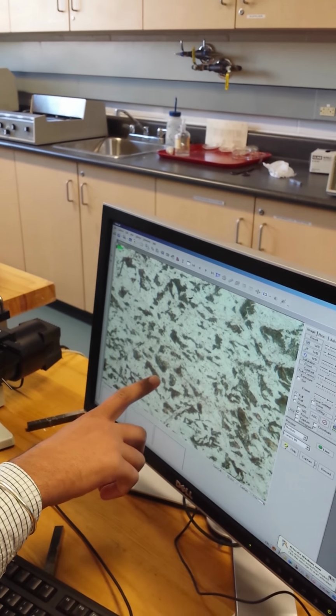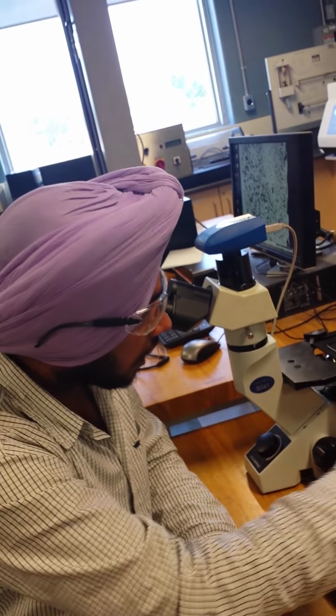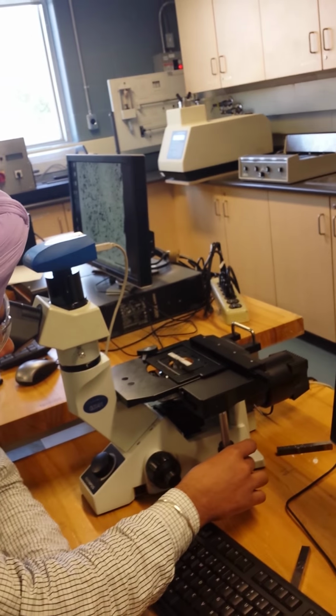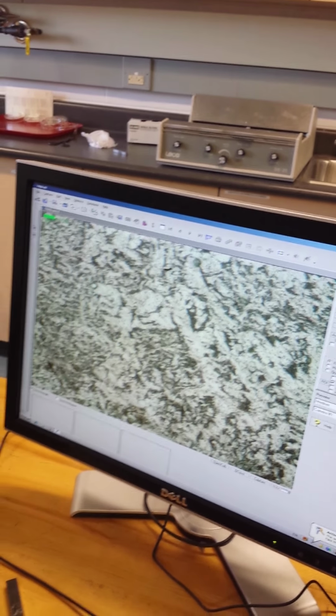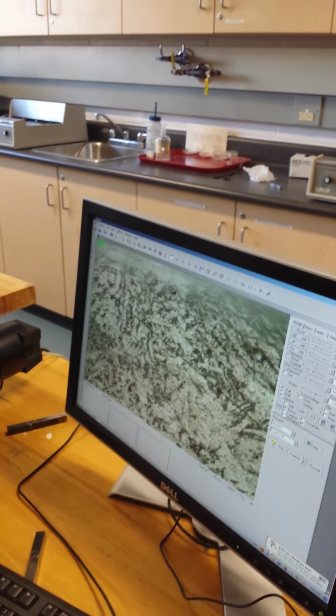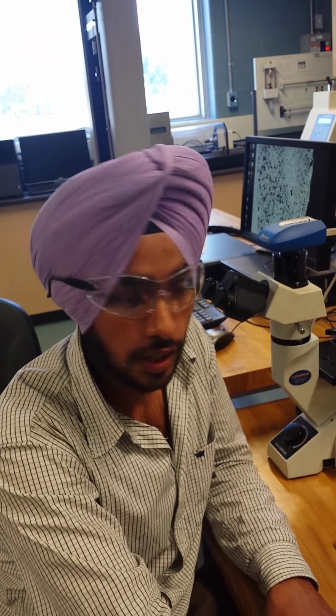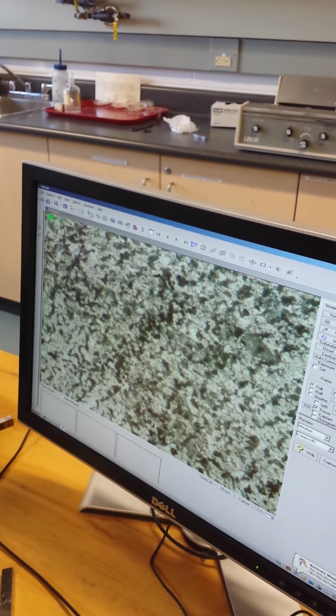This is the microstructure of the part from the extreme left-hand side, and we can see the grain sizes are much bigger on the left side. And as we move towards the middle part, the center part, we can observe that the grain sizes are much smaller than at the extreme ends. And same with the right part here. And in this way we got 5 captures of the sample from different positions, and we analyzed all the images.